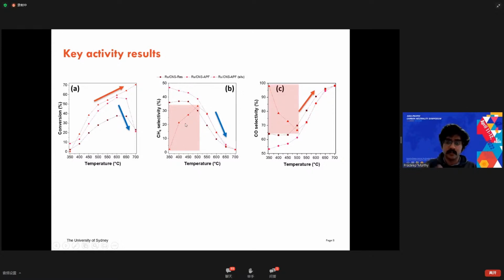Because there was some ruthenium discovered within the porous structure, this would have contributed towards more hydrogen being dissociated within the pores, and increased contact between carbon dioxide and hydrogen would have enabled more methane to be formed instead of carbon monoxide. That is the reason. Subsequently, methane decreased beyond that point, as the reaction becomes less significant when the temperature is increased, since it is exothermic.